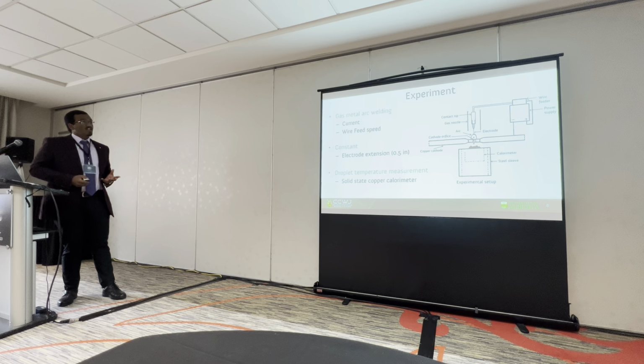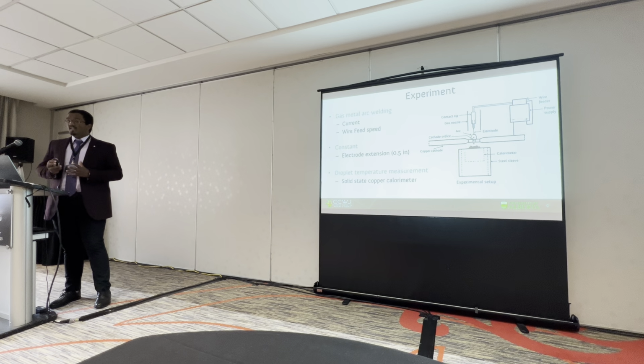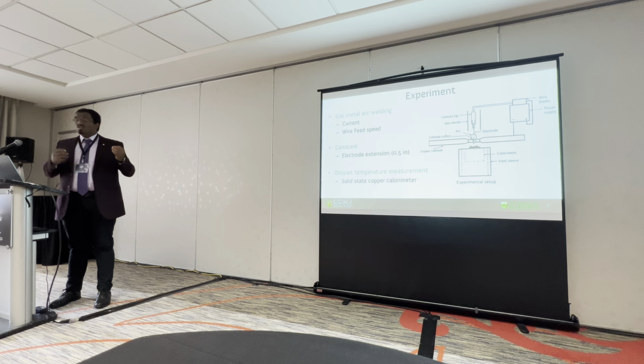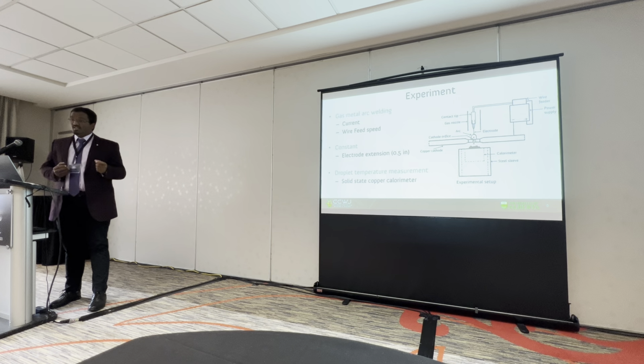The way we calculate the temperature is, once the molten droplet falls onto the solid state calorimeter, we have thermocouples fitted into the calorimeter, around 4 thermocouples. The copper calorimeter is designed in such a way that its Biot number is very low, in the range of 3.5 times 10 to the power minus 4. The low Biot number of that calorimeter helps it to have temperature homogeneity across the entire surface. Thus, any temperature measured across all the thermocouples is supposed to be a very close representation of the actual temperature of the droplet which falls into the calorimeter.